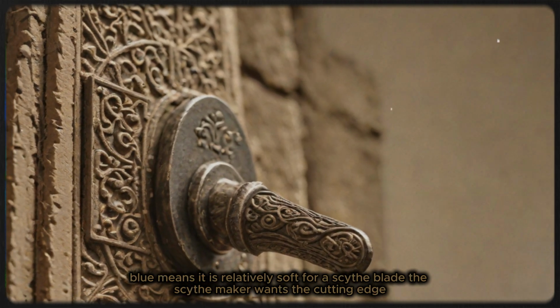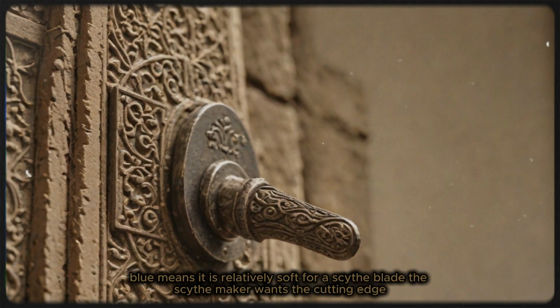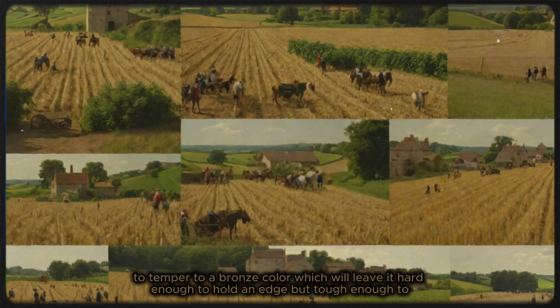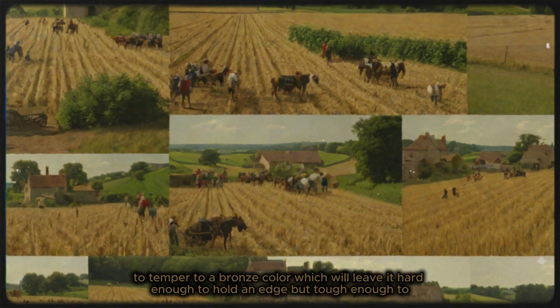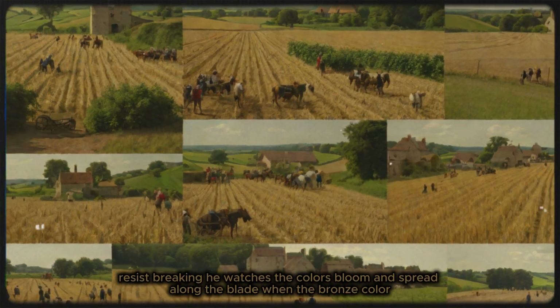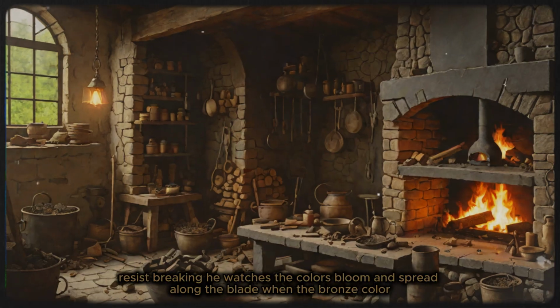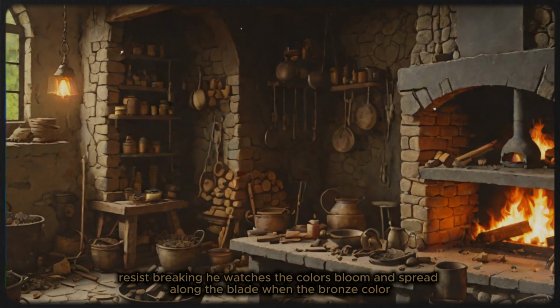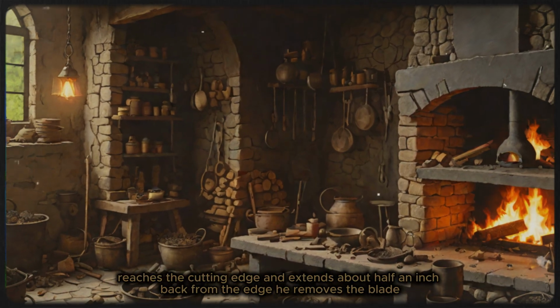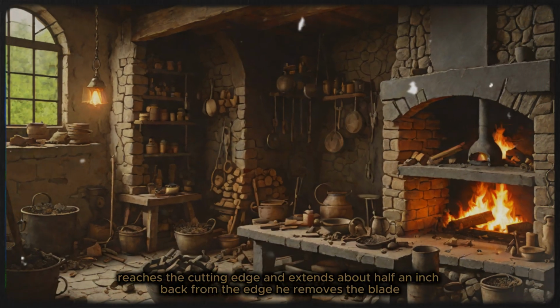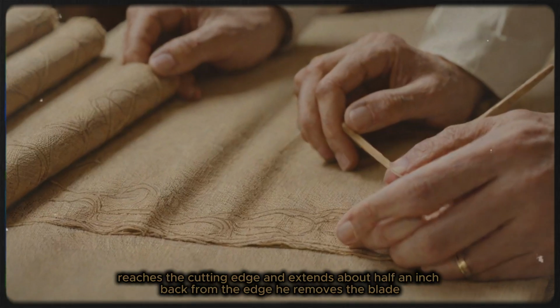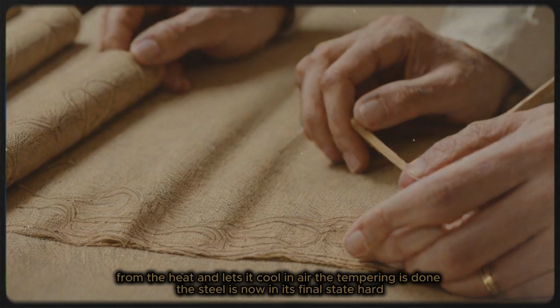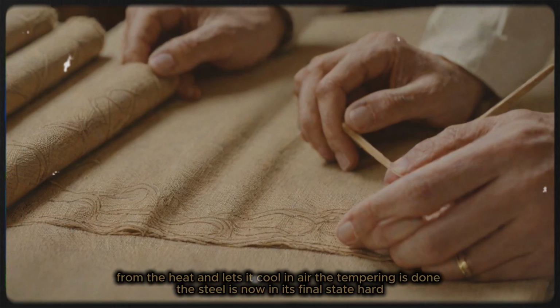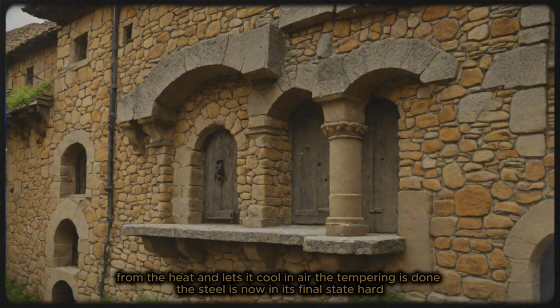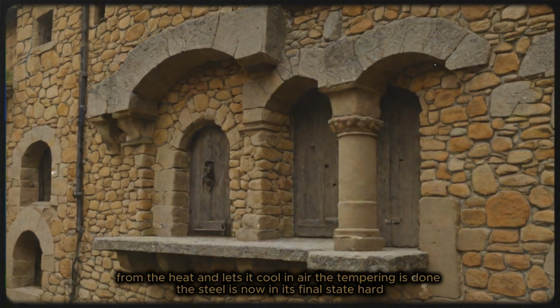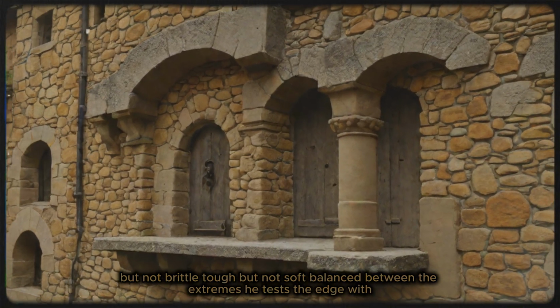For a scythe blade, the scythe maker wants the cutting edge to temper to a bronze color, which will leave it hard enough to hold an edge but tough enough to resist breaking. He watches the colors bloom and spread along the blade. When the bronze color reaches the cutting edge and extends about half an inch back from the edge, he removes the blade from the heat and lets it cool in air. The tempering is done. The steel is now in its final state, hard but not brittle, tough but not soft,